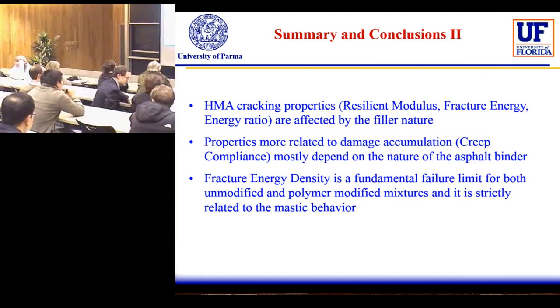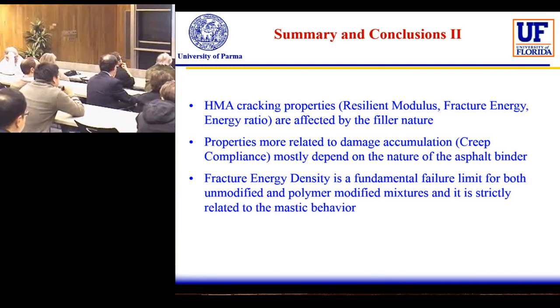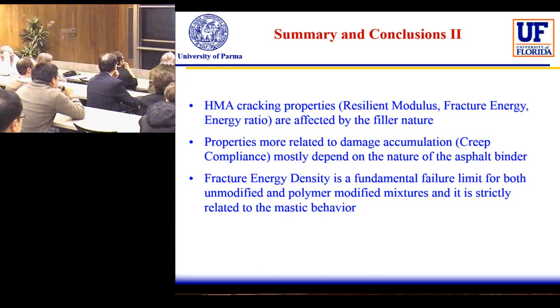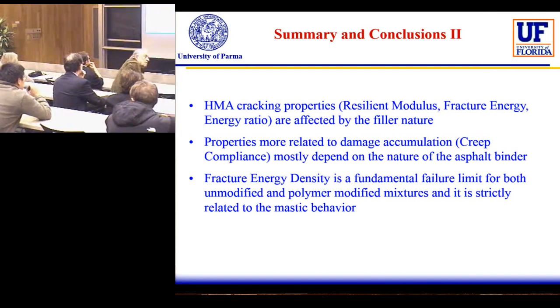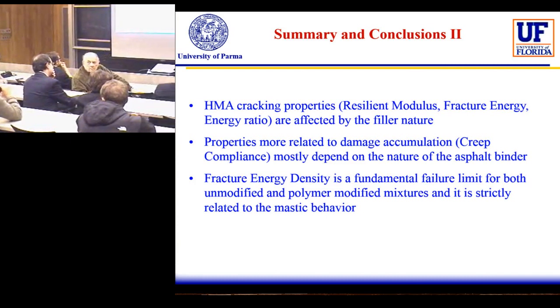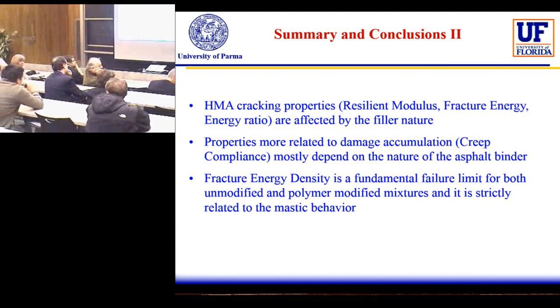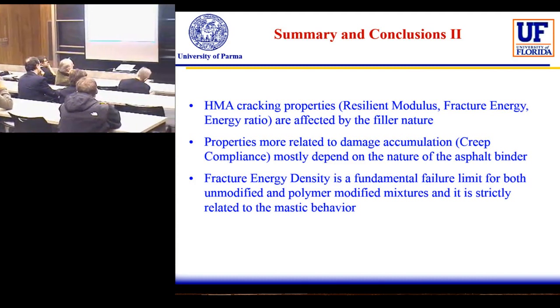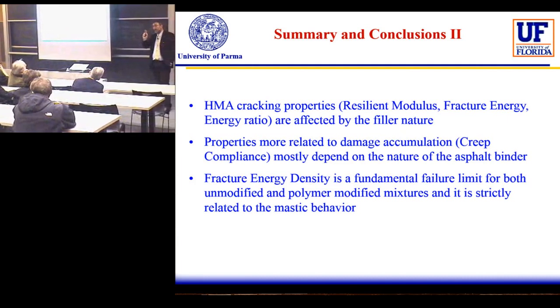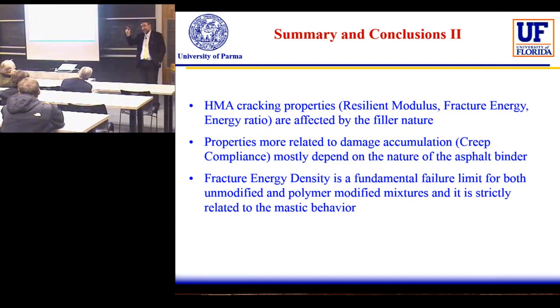Following Joe's question, when you define fracture energy density, I think this quantity will depend on specimen size, because the stress-strain curve will depend on specimen size. A large specimen gets more post-peak. The idea of the first fracture is to try to avoid the problem of the specimen size, to find the first damage in the material. Because if we have a big specimen, of course the stress distribution is related to the specimen.